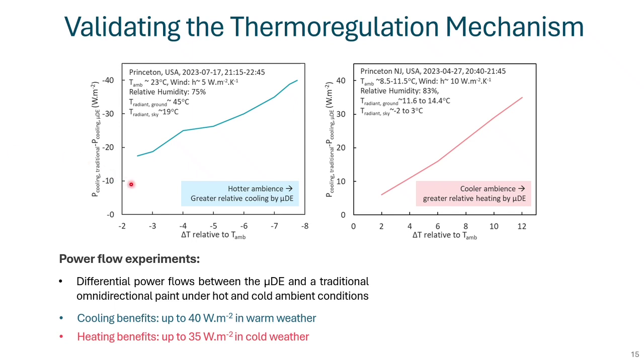In the left graph, we present the cooling benefit of the directional emitter in warm weather, reaching up to 40 watts per square meter, and in the right graph, we show the heating benefit under cold conditions, reaching up to 35 watts per square meter. These savings are fully passive without need of any external energy input.